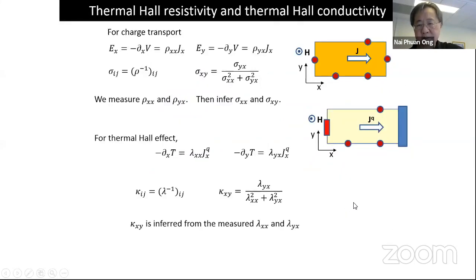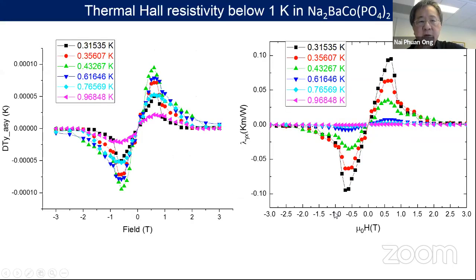Okay, so this reminds you that you don't measure kappa XY directly. You actually measure the thermal Hall resistivity, and then you invert that to get this well-known inversion expression, right? So here we're showing the thermal Hall resistivity. And this illustrates a problem that we will come back to in ruthenium chloride.